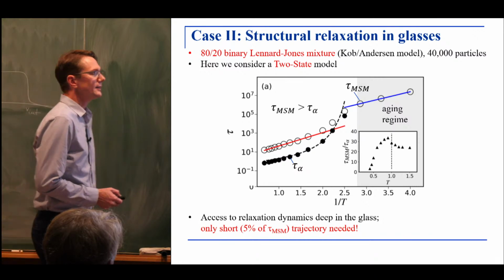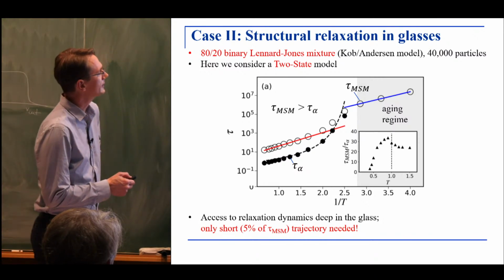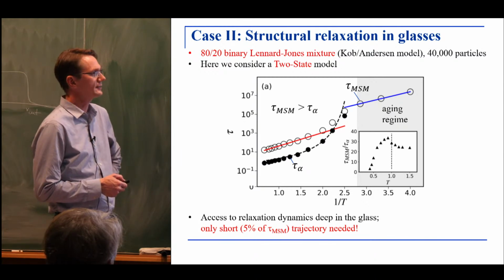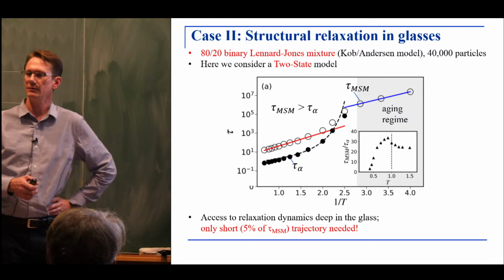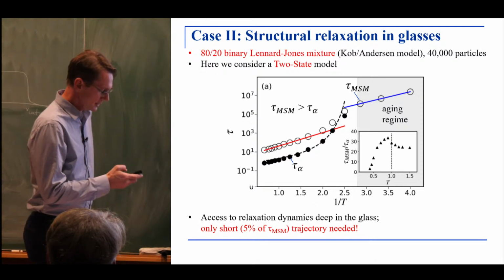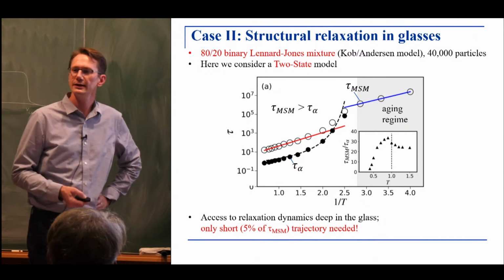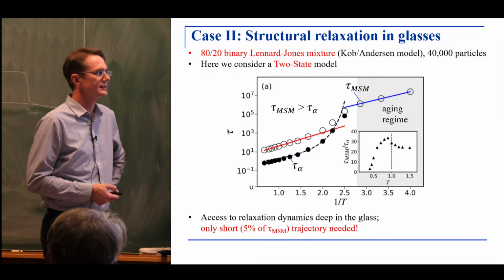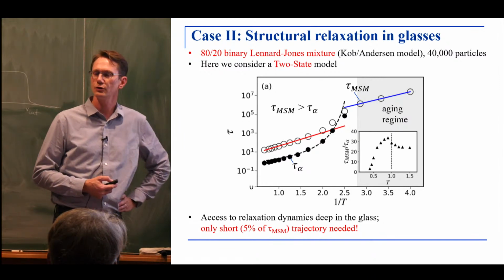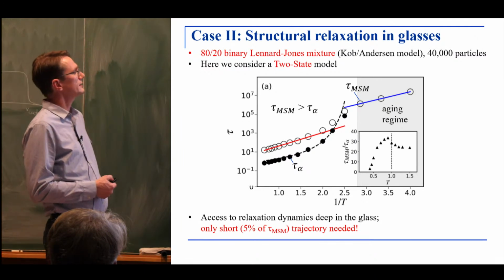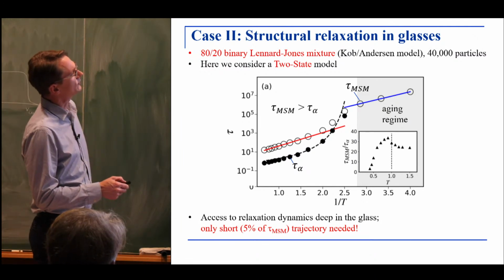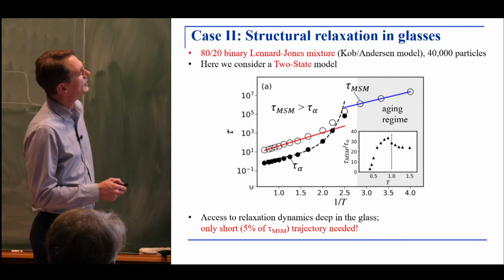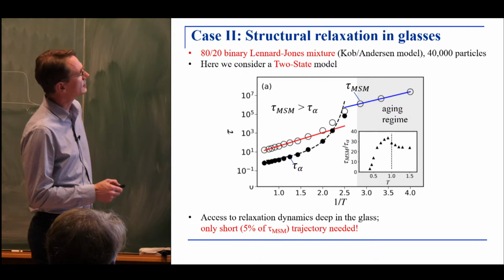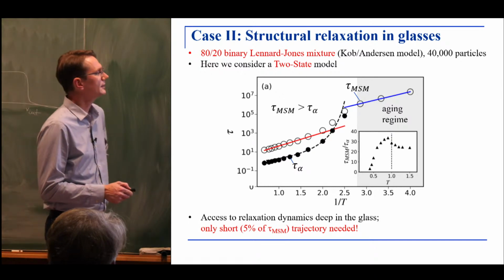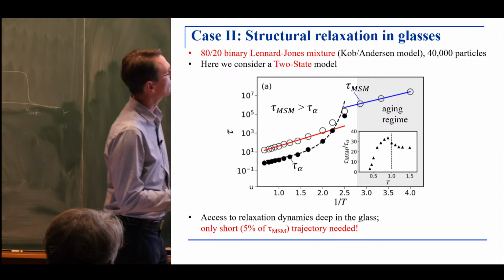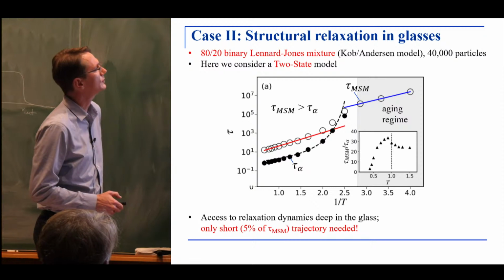The next thing I want to point out is that the time scale that we find here does not seem to be just the conventional alpha relaxation time, which is what is usually calculated, and we have seen all day being discussed here. So the alpha time was extracted using the standard definition. We calculate the decay of the self-intermediate scattering function, watch it decay to 1 over e, and read off the time scale. So the same quantity that you've seen all day. And it can be fitted with this VFT law, as has been shown many times here. But you can see that it is generally smaller than this MSM timescale here. And the inset, which carries the most important information, as always, shows you the ratio. It shows you that it's actually a non-trivial relationship between these two timescales.